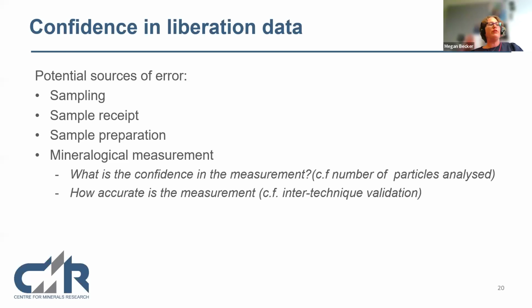Okay, so if you take a sample, you do your mill feed, mill product, and you want some liberation data. Let's first understand where the error can come in. So the biggest error probably is actually the sampling, and I've seen numbers of potentially up to 60% error related to sampling. We need to get representative samples, and for those of us doing the mineralogical measurements, we're trusting that whoever sampled the circuit or the drill core is giving us samples that are representative. We then need to know that when the sample comes into a lab, with the sample receipt and the chain of custody of the sample, there's no error from confusion or contamination or anything like that.